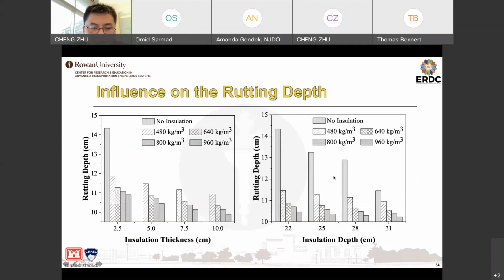So these are the results that we obtained. It's equivalent to the figure I showed just now. One is showing the rutting depth, which is calculated based on the MEPDG design. With more insulation thickness, we see a reduction in the surface rutting depth. And for the change of the insulation depth, we can also see the remediation effect on the rutting depth.